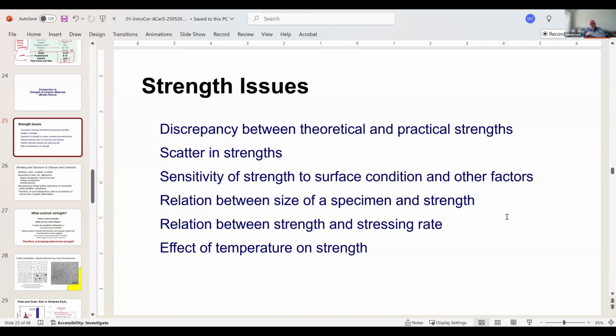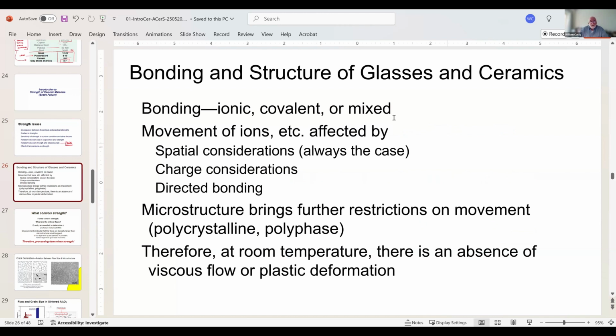But the problem with ceramics is that because of the way things are stressed, surface conditions become critical, because a defect at the surface then is in the highest condition of stress, and that's the one that will then propagate. We also find that larger specimens give us lower strength, okay? And in some cases, although it is rare, we may see that if we test things faster, our strengths go up. This is more true for glasses than for ceramics. And then if I go up in temperature, typically my strengths decrease.